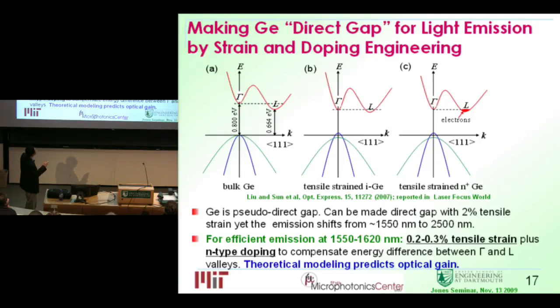So to keep what we call Fermi statistics, or keeping the level flat for these two bottoms, the electrons in this L valley will tend to scatter to here and further recombine, and that will give you efficient light emission. For those of you familiar with semiconductors, you do worry about the free carrier loss in here, but our modeling has shown that this transition is so powerful that it's enough to overcome the loss in here, such that you can get net gain and probably you can get lasing.